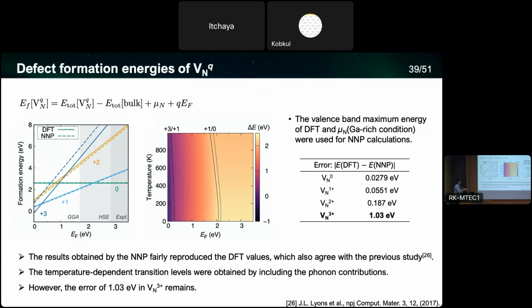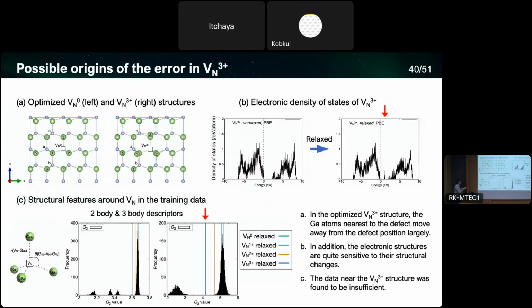And by including the phonon contributions, we can also see the transition levels as a function of temperature. Because we have a difference in the +3 charge state, we cannot see the transition at the left-hand side, but basically the predictions are quite acceptable. So we want to reduce the errors that appeared in the +3 charge state, and we have been thinking about what the reason was. And what we found is poor sampling. The +3 charge state has slightly different optimized structures compared to the other charge states.